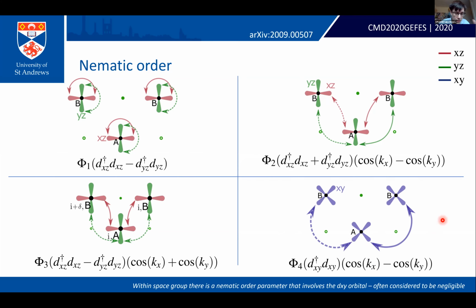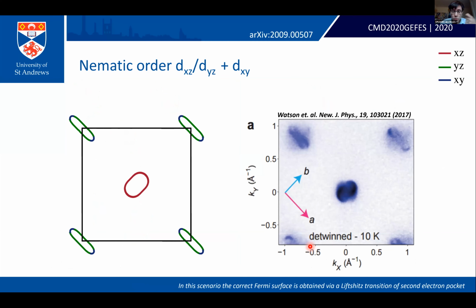Now, again, in most theories of the nematic state, this term is considered to be small or negligible. But we simply asked the question, what if that wasn't true? What if this term was actually large? Well, in that scenario, you can generate the correct Fermi surface as measured by ARPES. What you do is you generate a Lifshitz transition of that second electron pocket. You push it above the Fermi level.